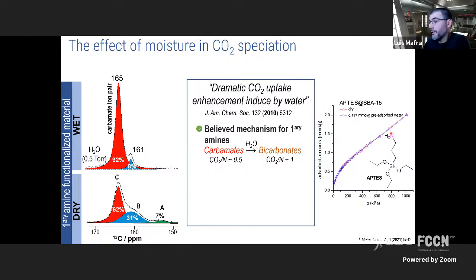So we tried to do some NMR on that. The dry samples show the typical spectra that we have seen before, A, B, C. Once you expose them to moisture, even with a very low amount of moisture, in fact almost nothing, a peak disappears completely, and you have a conversion of this B species, which is carbamic acid, to the ion pair, okay? So we tried to understand if this could be bicarbonate overlapping these bands. This could be. So we did carbon NMR of a tertiary amine, which cannot form carbamates or carbamic acid at all, and can only form bicarbonates. And the result is the following.